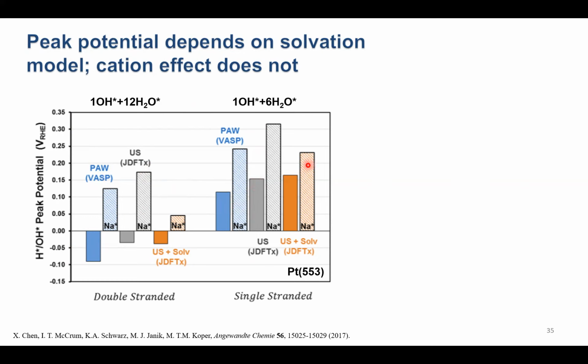Further, we can even add on an implicit solvation model on top of this. And we see, again, the cation still has the exact same effect. It weakens OH and water adsorption, at least for low OH coverage, and shifts the peak to more positive potentials.